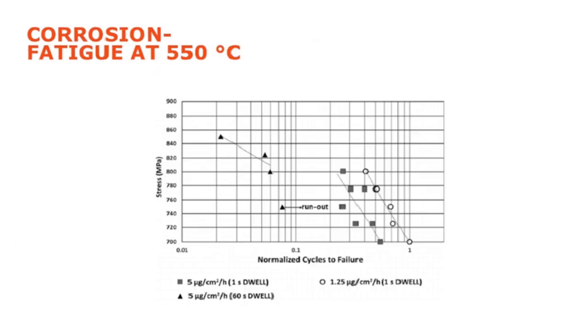So starting to introduce fatigue into the equation then. Now we've got stress cycling going on. This is quite a simplistic view of how this type of corrosion affects fatigue life of these alloys. And again, it doesn't tell the whole story, but it does start to help us unpick a little bit what's going on. We've got three curves on this stress cycles to failure graph, an SN curve. The first two, the square and the triangle, are 5 microgram fluxes, so that's the rate of deposition of our corrosive species, and the circle is a 1.25 microgram per centimeter squared per hour rate of flux deposition.